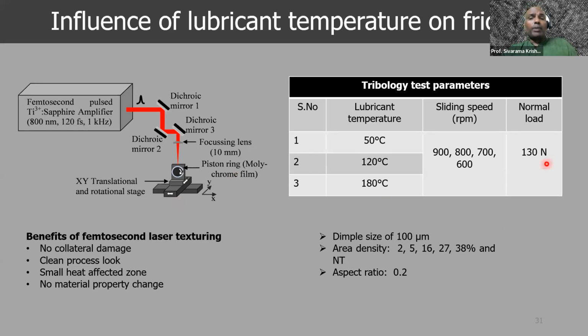I will conclude this little test case by presenting a few details of the effect of lubricant temperature on these grooves, on nanosecond textured versus femtosecond textured grooves. We used lubricants at 3 different temperatures, 50, 120, and 180 C, and different sliding speeds, 600 RPM all the way to 900 RPM, under a normal load of 130 newtons.